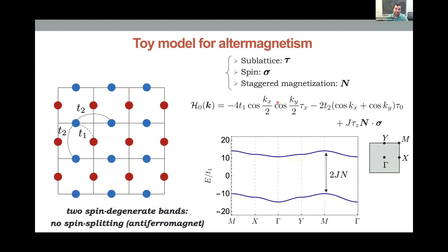We can go ahead and write down an effective Hamiltonian for this problem. You have 2 different degrees of freedom: the sublattice, which I'm going to call tau, and the spin, which I'm going to call sigma. I'm going to do a very simple model where I have local moments on the sites, that's the N, the staggered magnetization, that are Kondo-coupled to electrons that are just hopping around, with nearest neighbors and next nearest neighbors. You can write down this model, and if you solve it, you find that nothing happened. The spin bands are still degenerate.